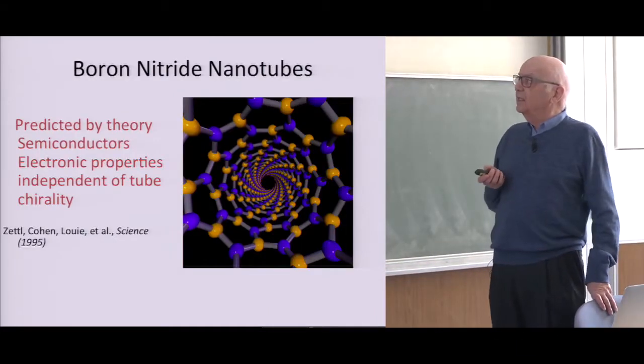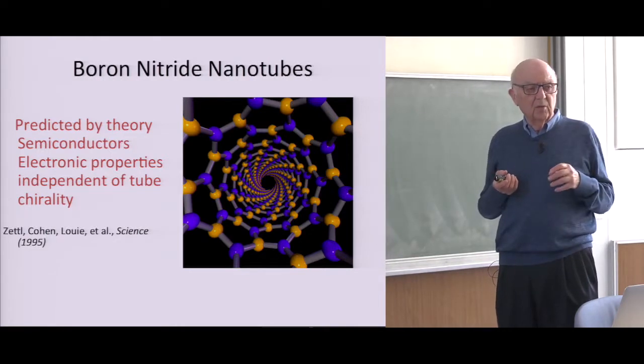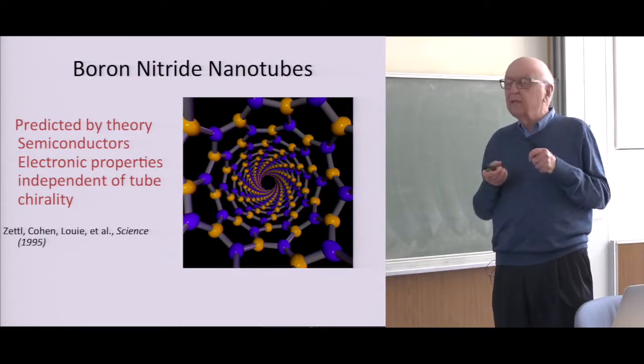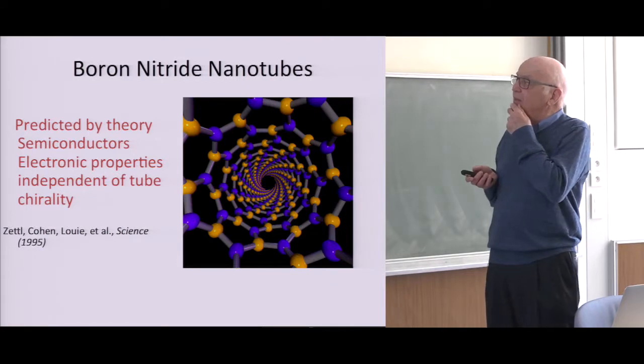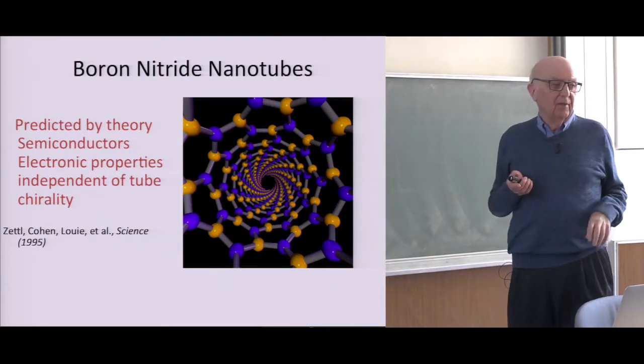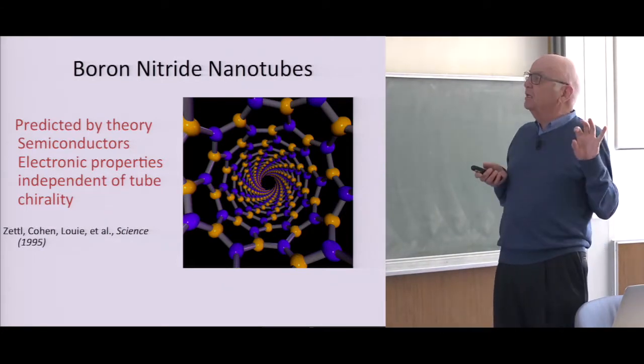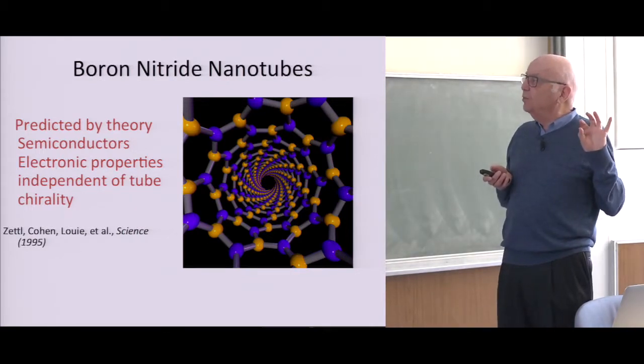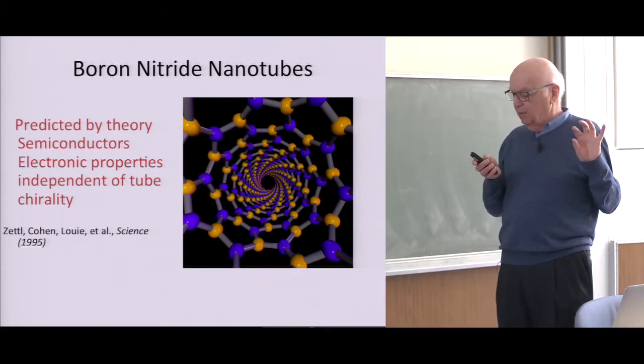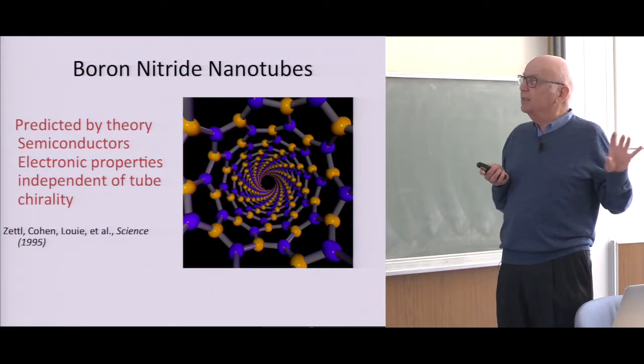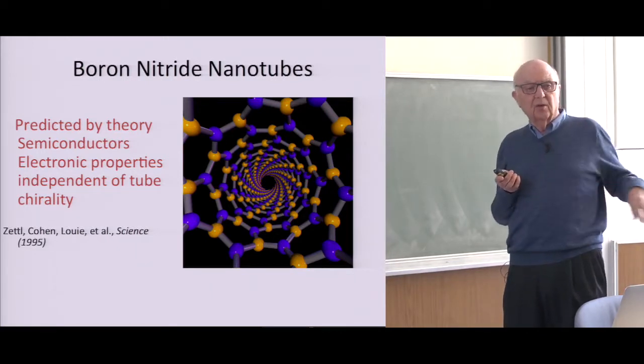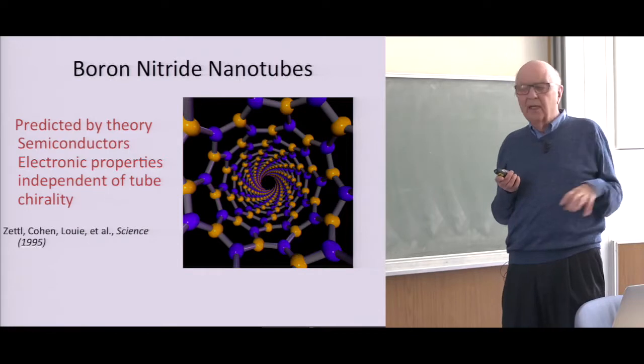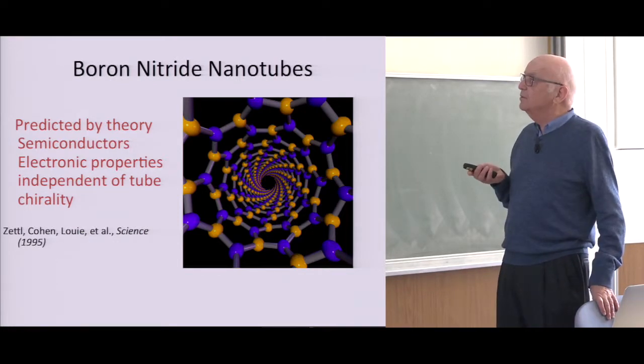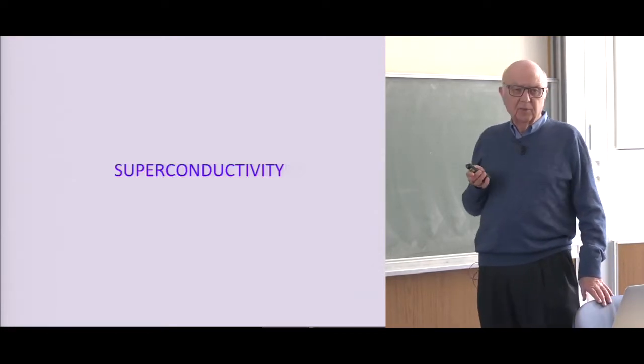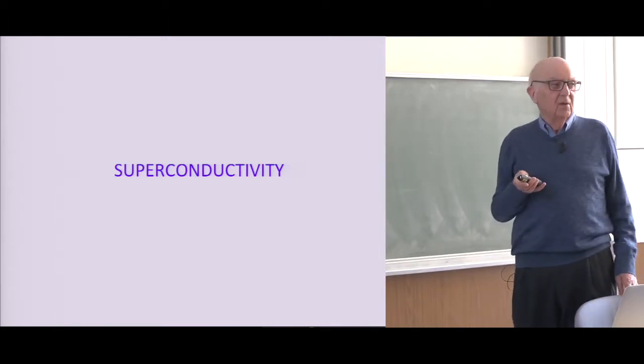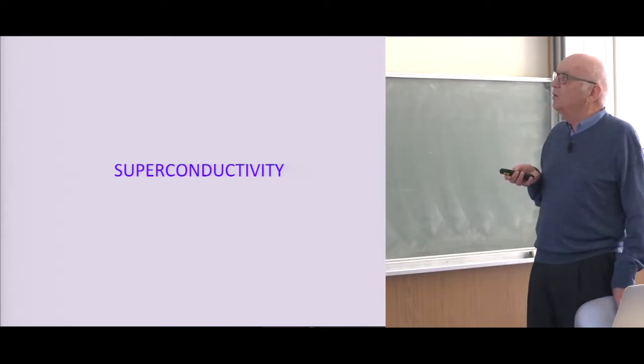Another thing is that instead of having carbon nanotubes, you have boron nitride nanotubes, and again, predicted on the computer, and we have them. And they're wide band gap semiconductors, which if you put an electric field on, you can make the gap get smaller. But unlike the carbon nanotubes, where you get a mixture of semiconductors and metals, these are all semiconductors. Okay, a little bit about superconductivity. I want to end with something quite new.